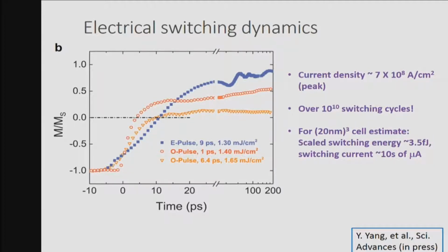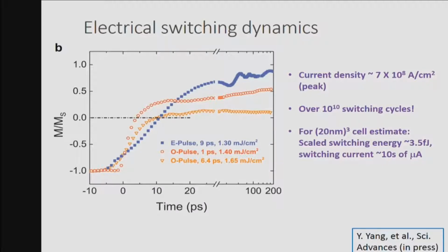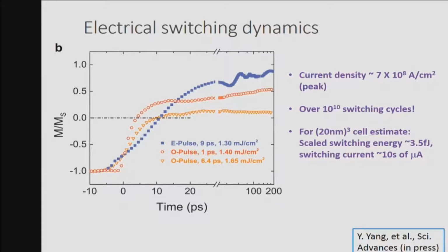This experiment is done by running at high repetition rate with the laser running at about 100 kilohertz repetition rate. And we scan slowly to acquire all this data. There's quite a bit of averaging. We measured many different times and varied various different things. This particular sample was subjected to over 10 to the 10 electrical pulses with no evidence of any kind of degradation.